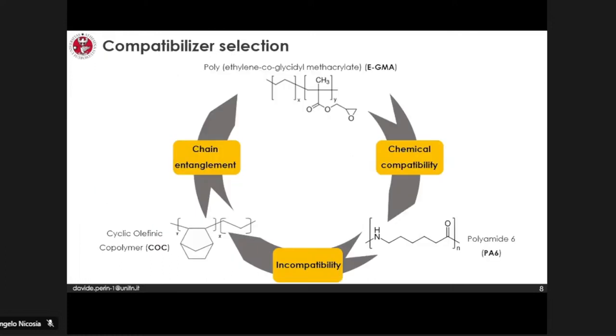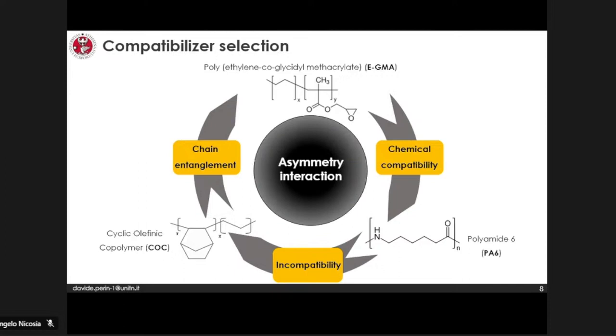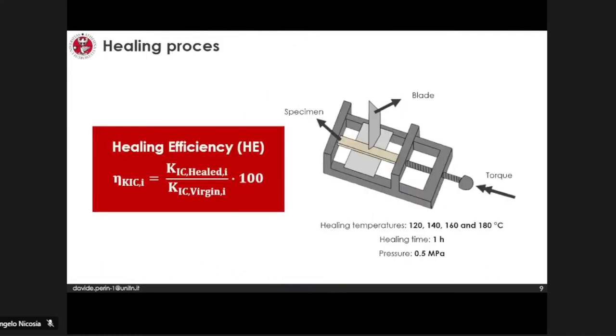The compatibilizer selection was pretty tough. I selected 5 different compatibilizers and studied everything, but the best one was EGMA, because this compatibilizer is able to chemically react with polyamide 6 and has the possibility to create the so-called chain entanglement with COC. This particular interaction goes by the name of asymmetric interaction. It is quite fundamental for self-healing polymers, because this interaction does not hinder the flowability of the cyclic olefinic copolymer. Switching to how I evaluated the healing efficiency, I performed 2 different types of fracture toughness tests, one in quasi-static mode and the other one in impact mode.